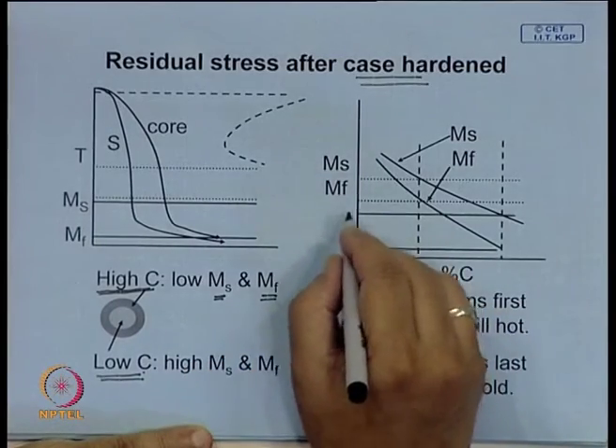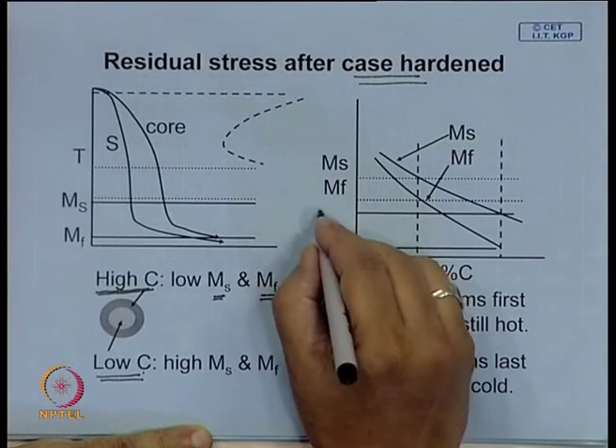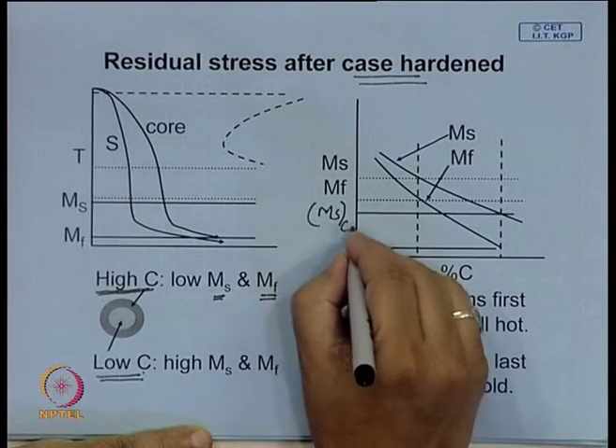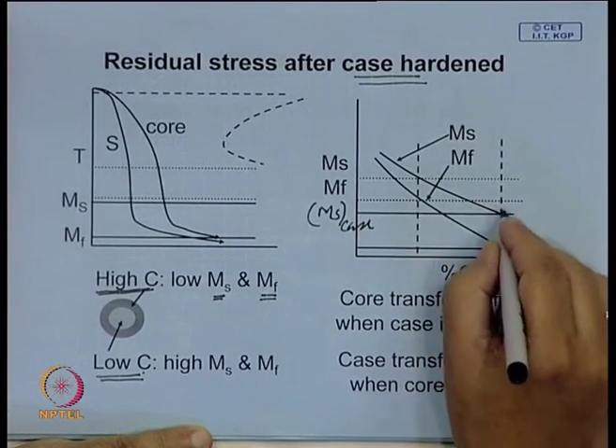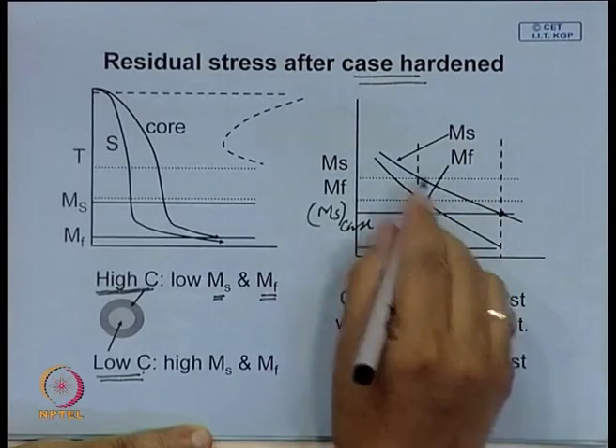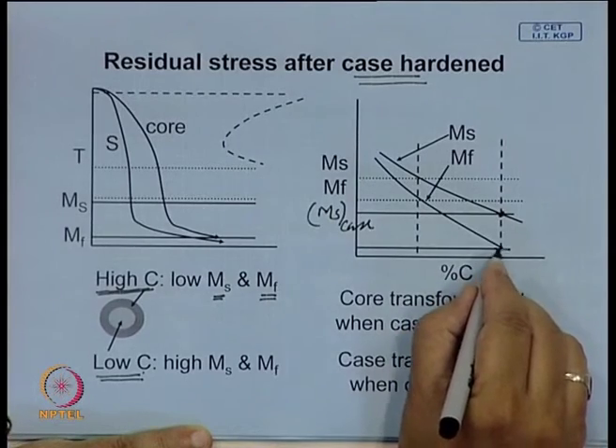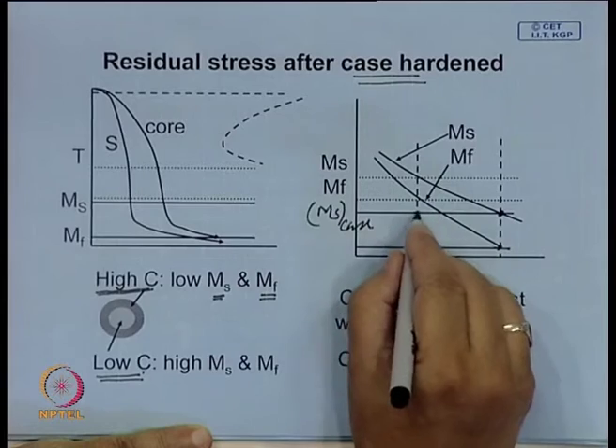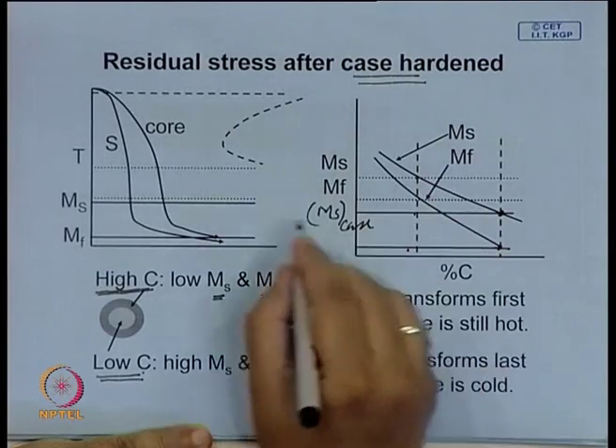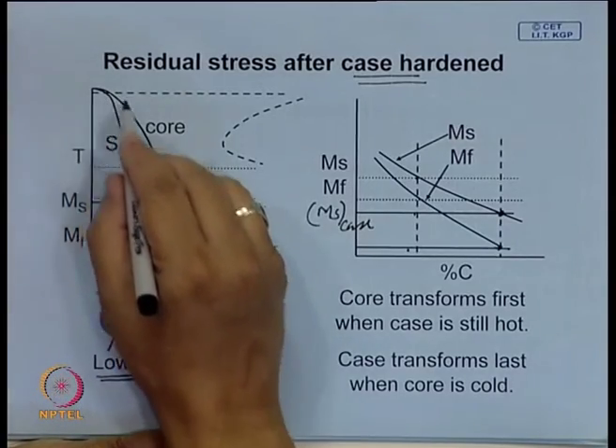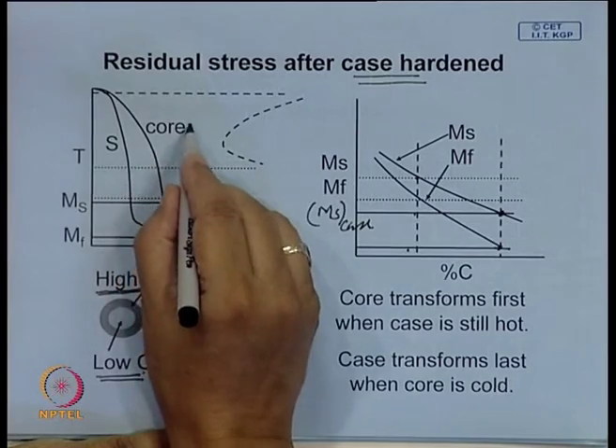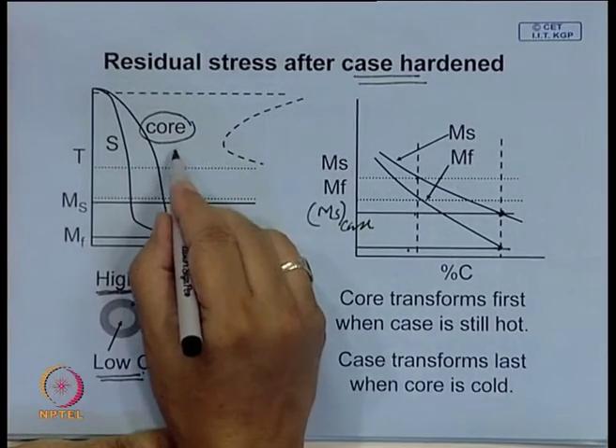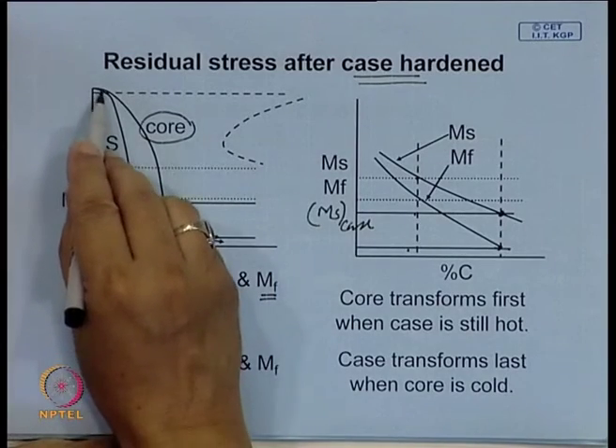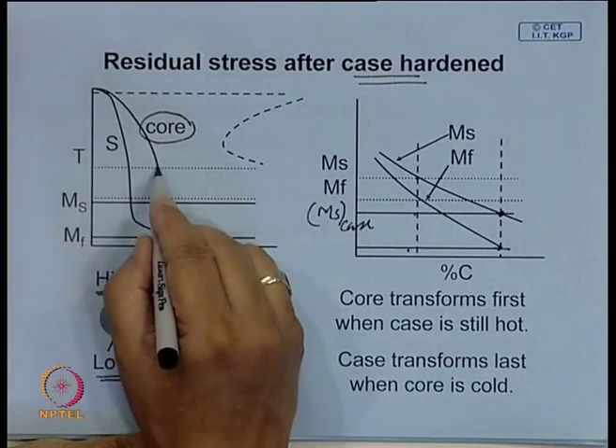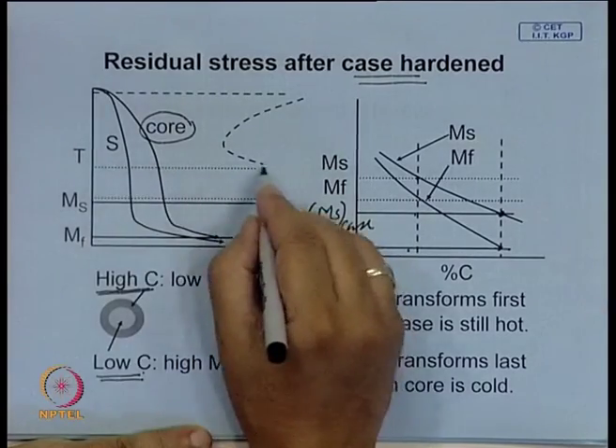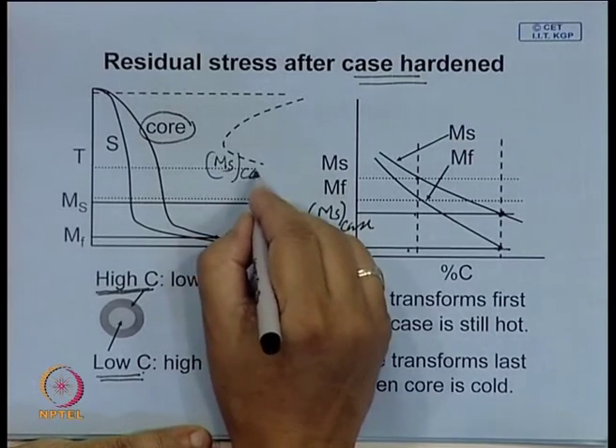So you will find that this is the MS temperature of the case, because the case has high carbon content. This is the MS temperature, and this is the MF temperature. So the case has lower MS and MF temperatures than the core, and when you quench this job, or try to cool it fast, the core, which is the inner portion, will always cool more slowly than the surface. But in spite of this, you see the core crosses this MS temperature for the core, this is the MS for the core, before